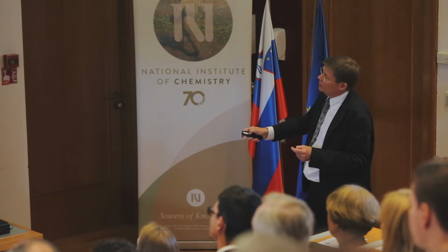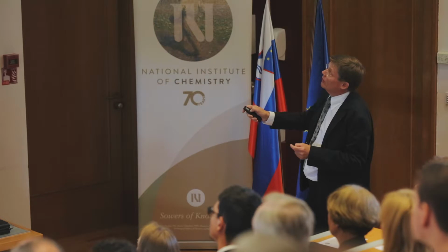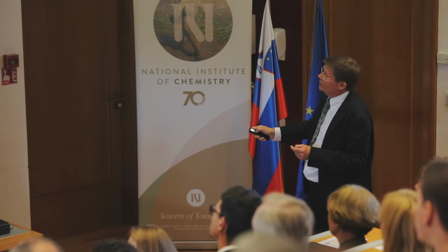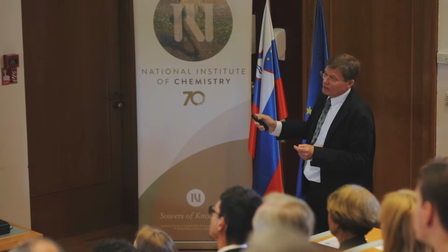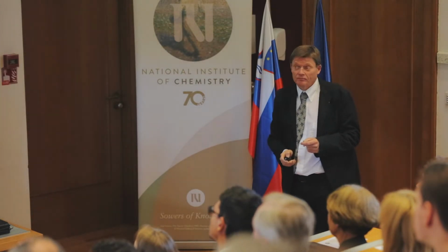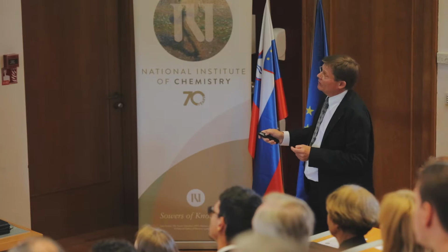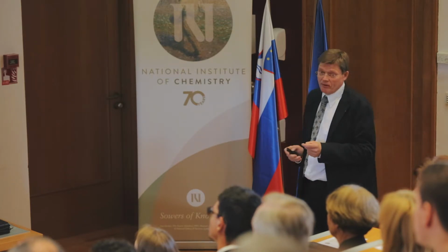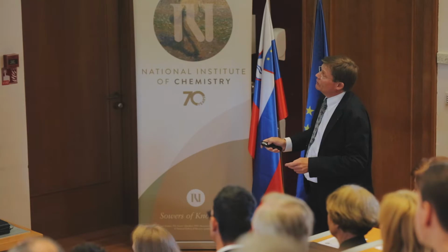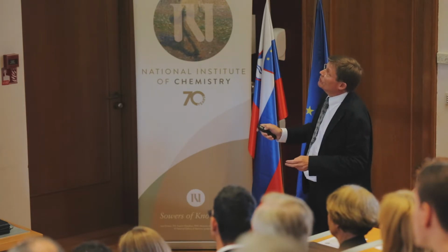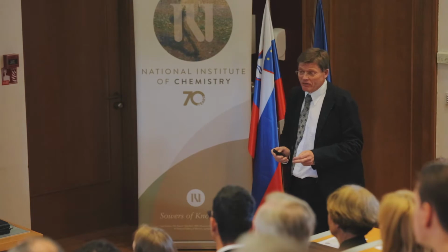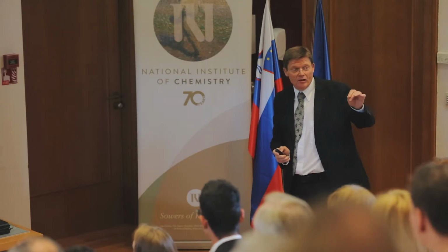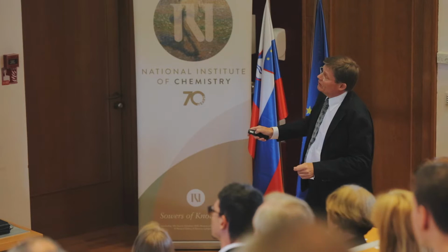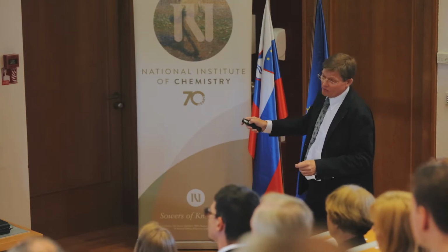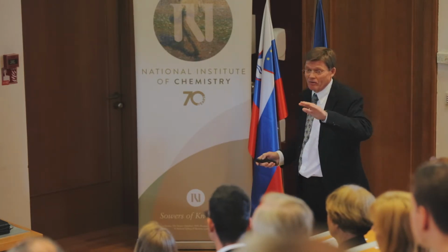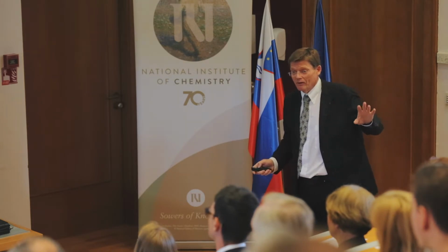So here you get the total resistance, which is ions and electrons in parallel, and at the very end you get the non-blocked one, the electronic resistor left. The frequency dependence now corresponds to the time dependence. So it's not an ideal semicircle because this capacitor is not an ideal capacitor. Remember this transmission line characteristic. This is giving rise to what's called Warburg impedance, a 45-degree increase. So this is the same as the square root t law in diffusion in the time domain.